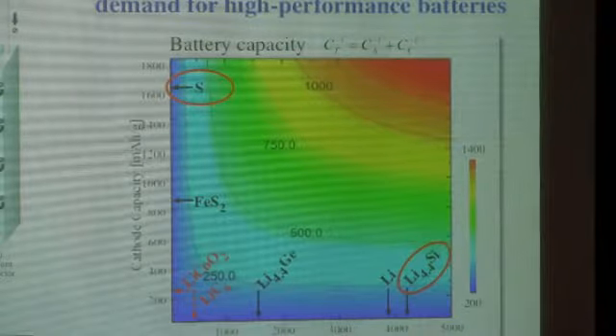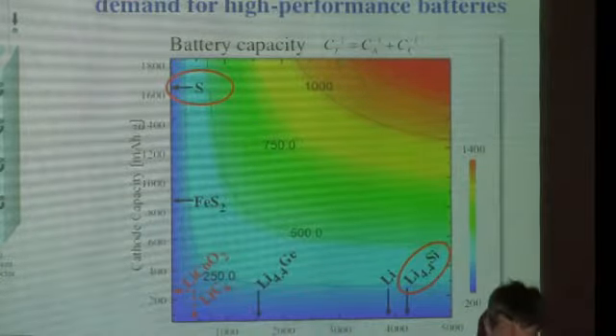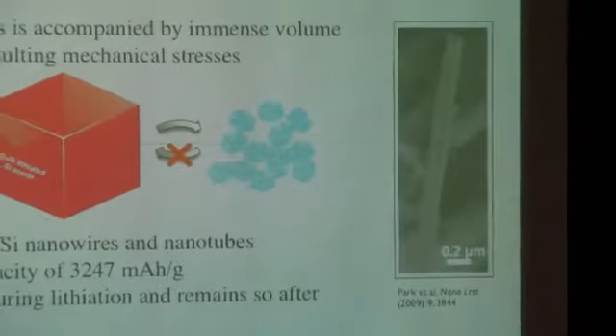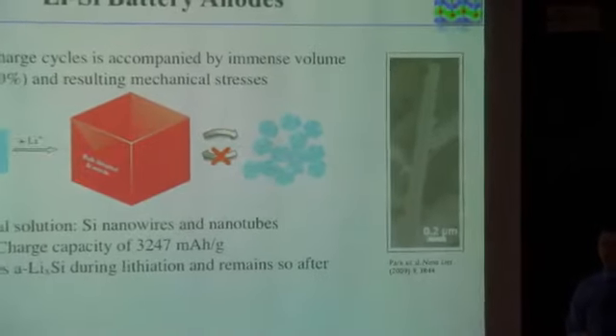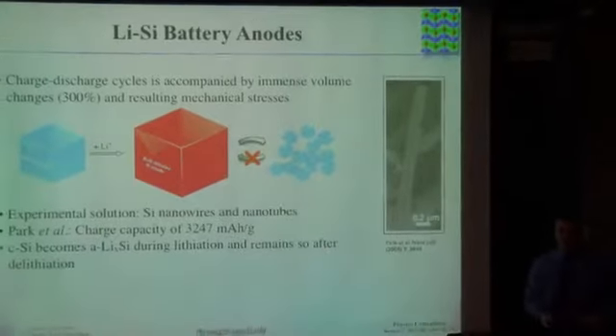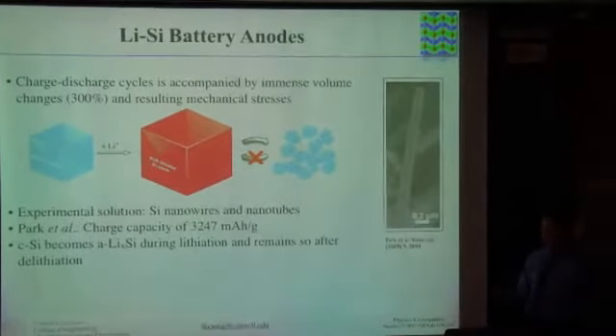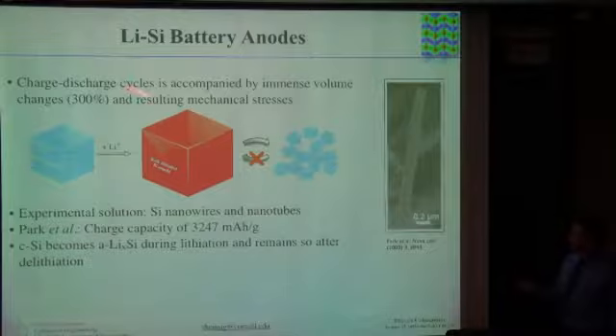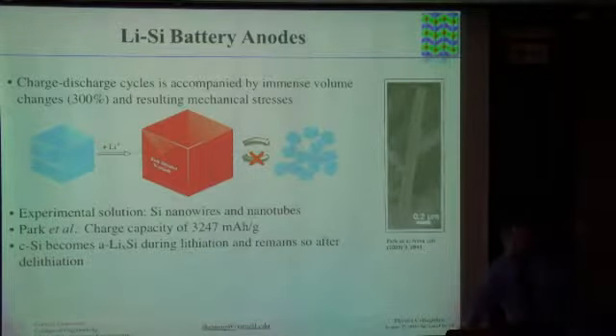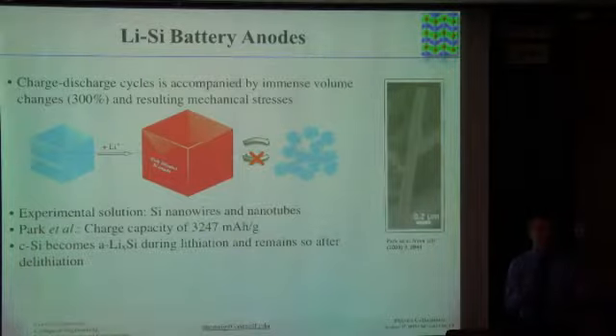So the first question is, then why in the world are we not doing that? We should be using lithium silicon and lithium sulfur. And the problem is that silicon, when you put into a silicon crystal 4.4 lithium atoms for each of the silicon atom you have in there, that thing swells. And it doesn't swell a little bit, it swells a lot. It swells by a factor of 3 to 4. And if you ever try to put something in a material and have its volume changed by more than 10%, you're going to find that it turns into a nice fine powder. And that's not good for a battery because the electrons won't move anywhere because suddenly it's all broken up. The battery will be dead after the first cycle.